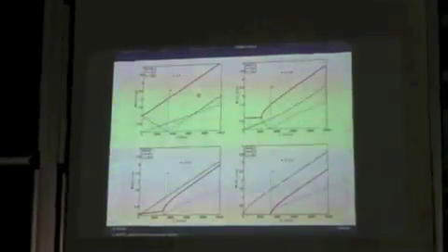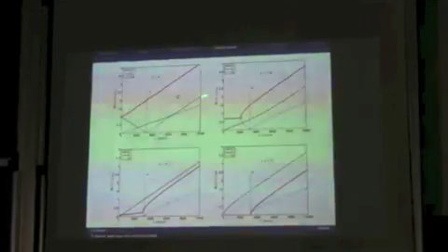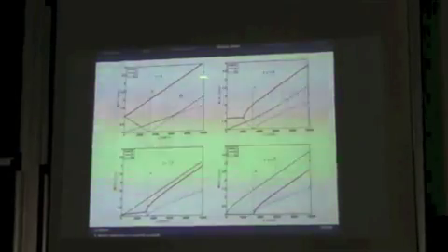Here you see the situation where the plane wave propagates in the same direction as the Burgers vector of the screw dislocation. And you see the dispersion relation. You see two almost shear waves here and one longitudinal wave in this direction. Here this line corresponds to the shear wave without defect.